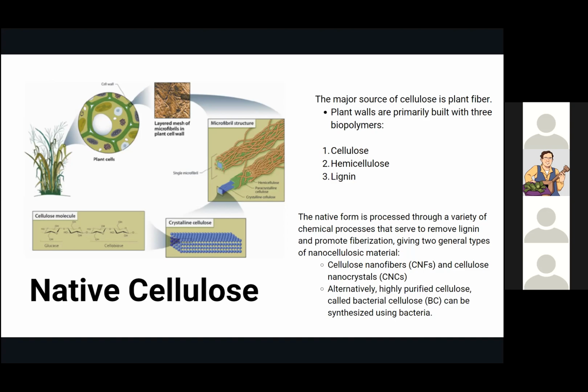So compared with plant cellulose, bacterial cellulose is very pure. It contains no hemicellulose or lignin and only a very low amount of carbonyl and carboxyl moieties. It possesses the highest crystallinity, excellent water absorption capacity, and extraordinary mechanical strength. And then between cellulose nanocrystals and cellulose nanofibers, the crystals have much higher aspect ratio and crystallinity, and the fibers have a semi-crystalline structure that provides them with increased flexibility and stability and stable thermal properties for use in flexible electronics.